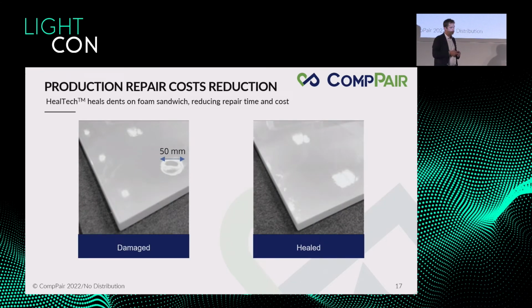We've mentioned production repair cost reduction before, and this was the example I was mentioning on foam sandwich panels, and this is also of interest if you're playing with the right foam and the right interface as well. You can really recover large dents, 50 millimeters in that case, and this was typically for a boat manufacturer in France who was spending on average 2 days to repair such kind of damage, and using our products, it's not 2 days anymore, it's just 2 minutes.